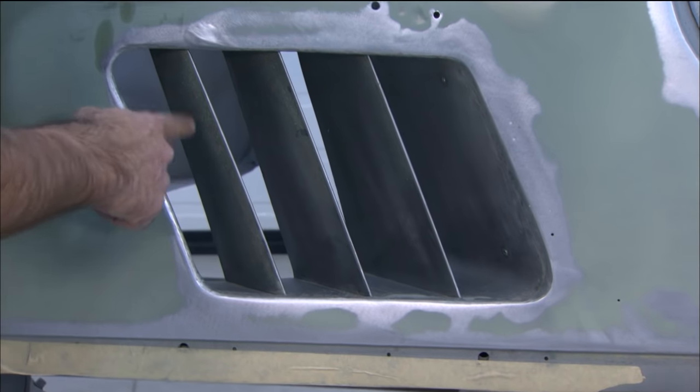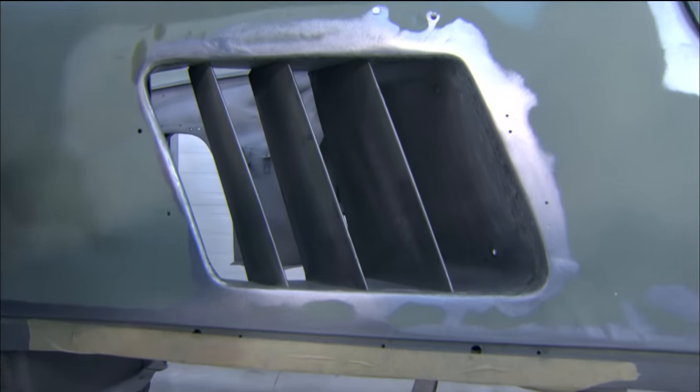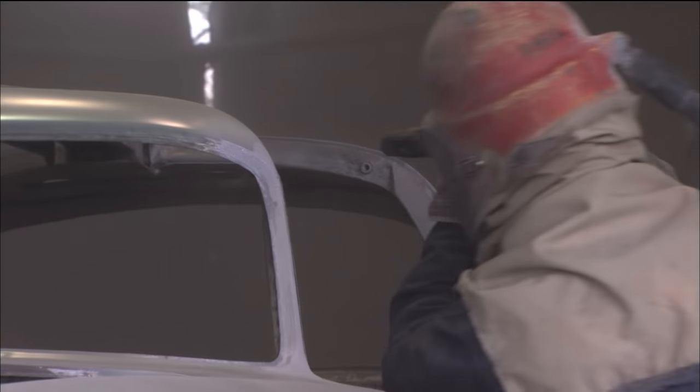If you look in the louvers, you can see it would be really hard to strip them with a machine or by hand, so the best thing here is to use baking soda. On the Mercedes there were some air dams on the side fenders and back scoops that you can't get into by hand or with any power tools. You don't want to use conventional sandblasting because the metal is thin and it will distort, so we used the soda. The soda gets into all the cracks and crevices and takes off the heavy paint, body fill, and tar cement. We also used walnut shell and corn cob in the wheel wells because they were heavily caked with tar. The bulk of the blasting on the Mercedes was done with black sand — all the window openings, door jams, and basic floor, anywhere the steel is a heavier gauge and rusty. Bottom line: there are a half dozen different ways to strip a car, each with pros and cons, but you'd better trust the guy holding the blasting nozzle because he can absolutely ruin a car if he doesn't know what he's doing.